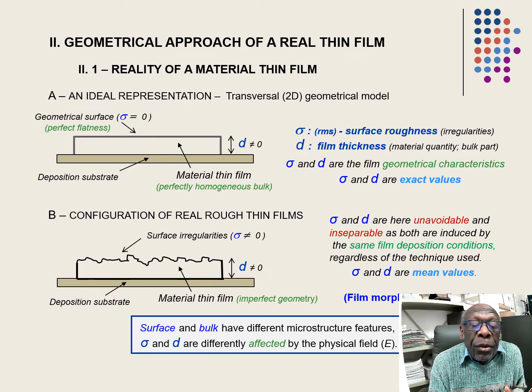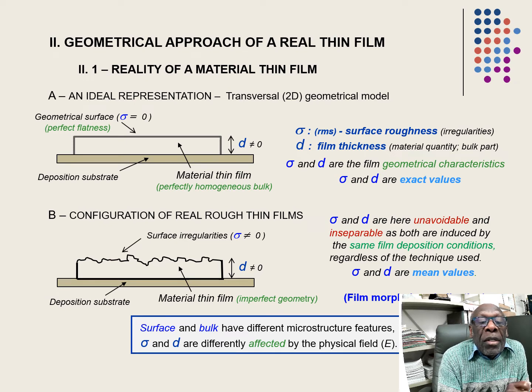Let's go now to real material thin films obtained from deposition conditions, whatever the deposition process, whatever the conditions used. In that case, the film surface always has surface irregularity at different levels, of course. One important point: the surface roughness represented by sigma and the thickness D of the films are unavoidable first. Secondly, they are inseparable because both of them are induced by the same deposition process and conditions. Here, D and sigma have mean values only. They are the indication of the film morphology.